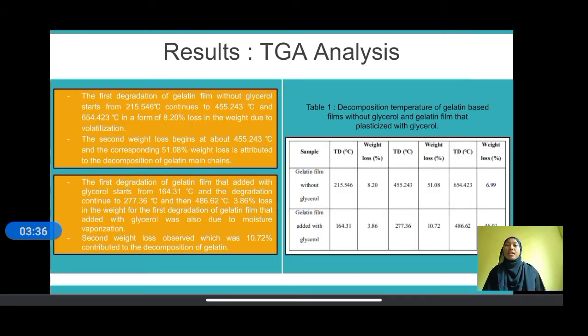Then this is the result for the TGA analysis. The decomposition temperature of the gelatin-based film without glycerol is much higher than that of the gelatin film added with glycerol.